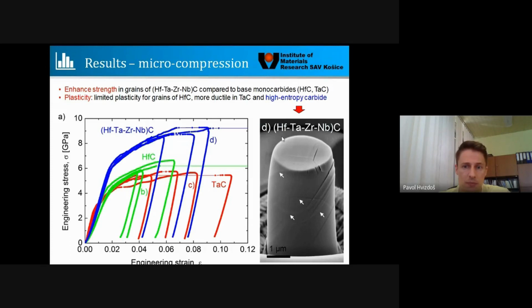Considering the last one, which was the most important, it's the high entropy carbide indicated in blue. What we can see first is that it has a significantly enhanced yield point. Instead of 4 or 3, it's 6 or even more. Regarding the deformability, it's at least as good as hafnium carbide or similar to tantalum carbide. So it means that there is something which can deform, at least at that specific orientation we selected, similar to tantalum carbide, but has enhanced hardness or strength.